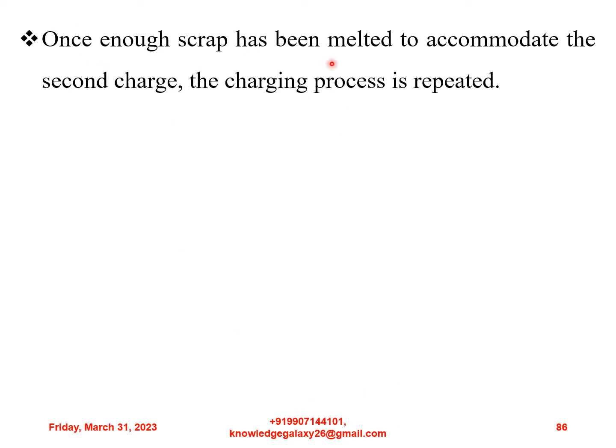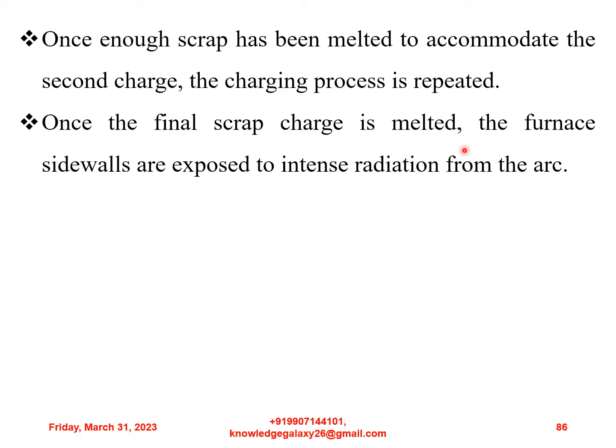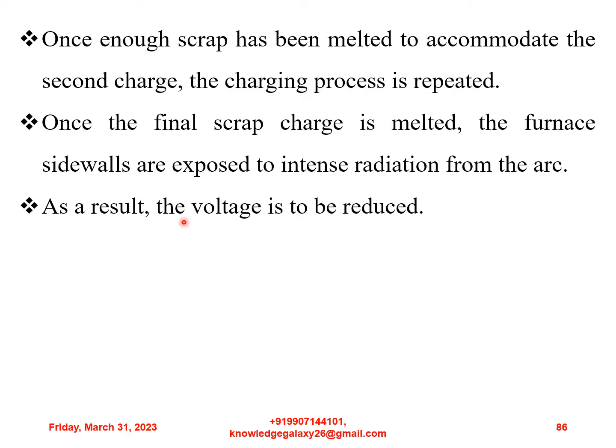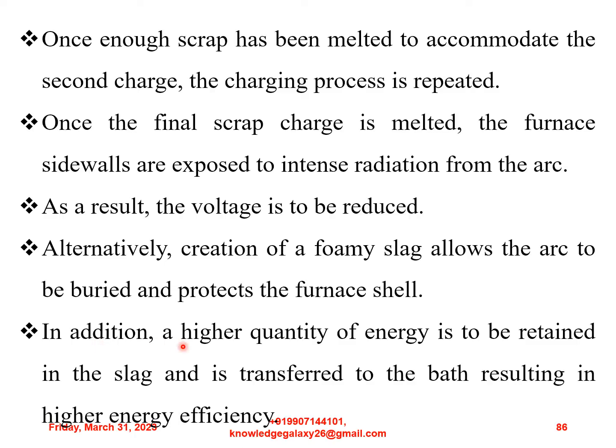Once enough scrap has been melted to accommodate the second charge, the charging process is repeated. Once the final scrap charge is melted, the furnace sidewalls are exposed to intense radiation from the arc. As a result, the voltage is to be reduced. Alternatively, creation of a foamy slag allows the arc to be buried and protects the furnace shell. In addition, a higher quantity of energy is to be retained in the slag and is transferred to the bath, resulting in higher energy efficiency.